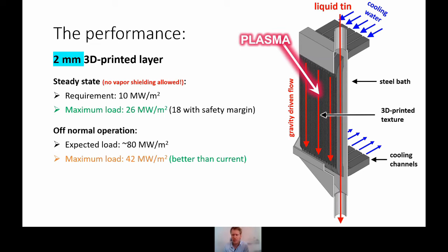In off normal operation, so let's say we lose the control of the plasma for a little bit, we could expect the heat load to go up significantly to about 80 megawatt per square meter. And this is too much still. I would predict we can dissipate around 40 megawatt per square meter. That is much better than the current state of the art, but still it's not enough.